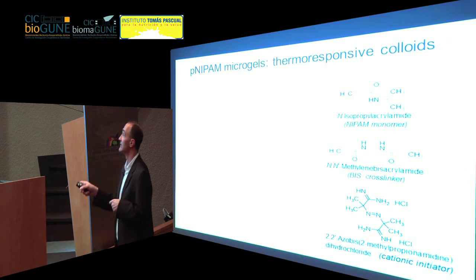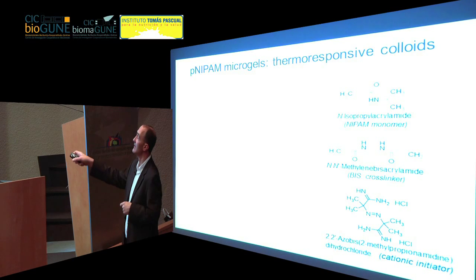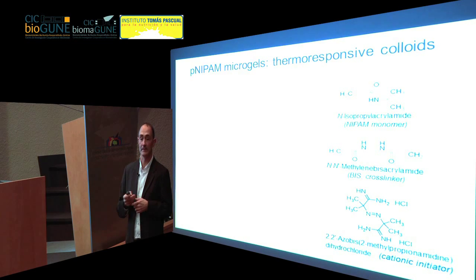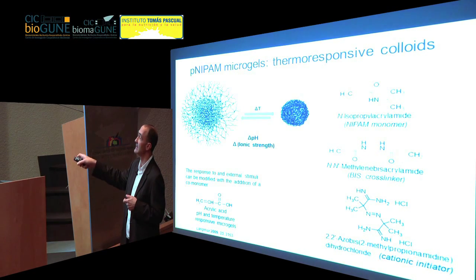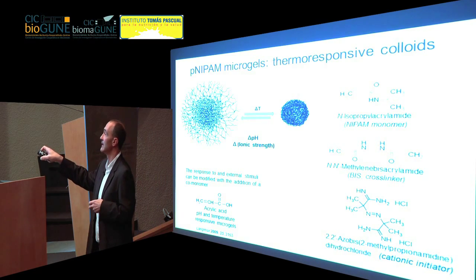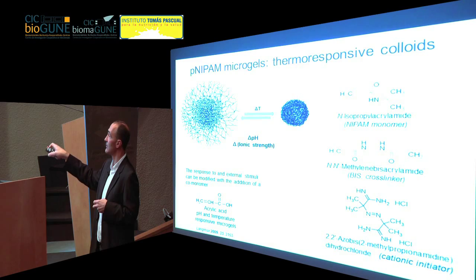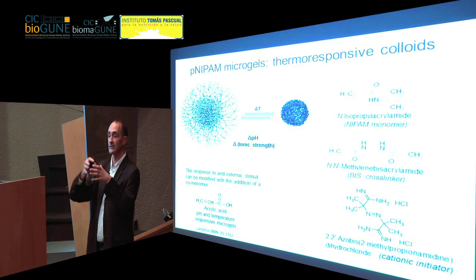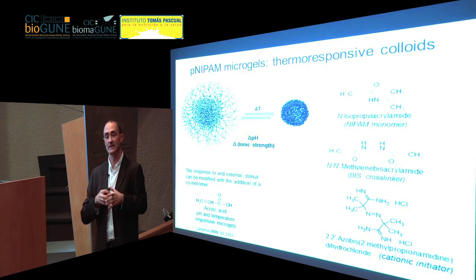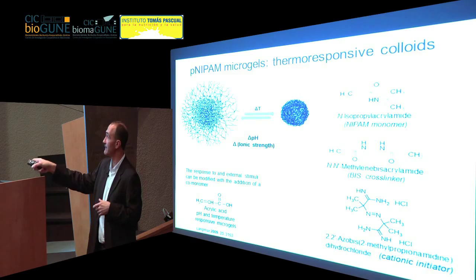And the final example is related to smart polymer systems, which are these poly(N-isopropylacrylamide) microgels. These are made from this monomer and a cross-linker, and you need, of course, an initiator to promote the polymerization. If you do this in appropriate conditions, you may be able to fabricate nice colloidal spheres, which have a really interesting behavior, because the composition of the polymer makes it so that at a certain temperature there is a phase transition, from an open state to a collapsed state. So there is a big change in the dimensions of the particles above a certain temperature.